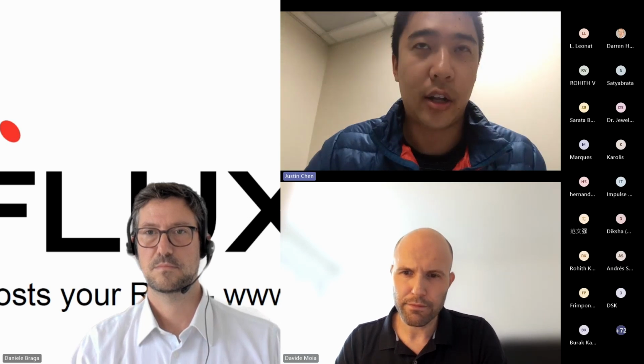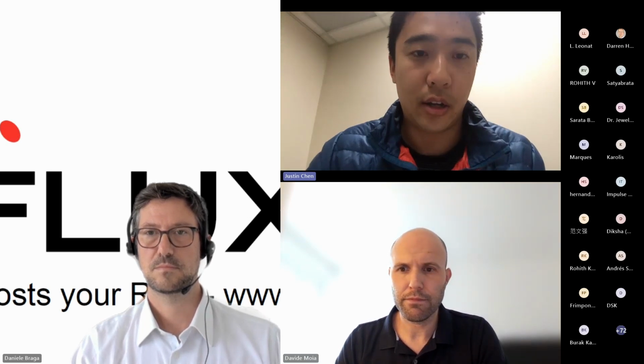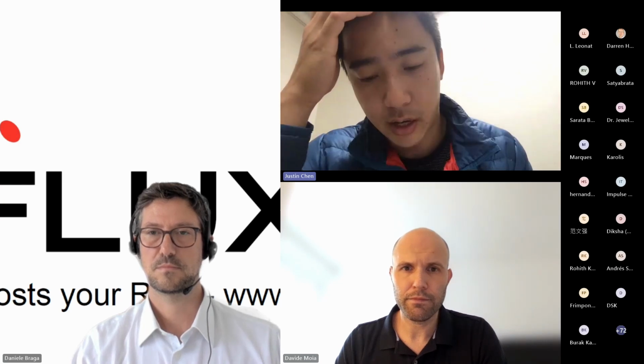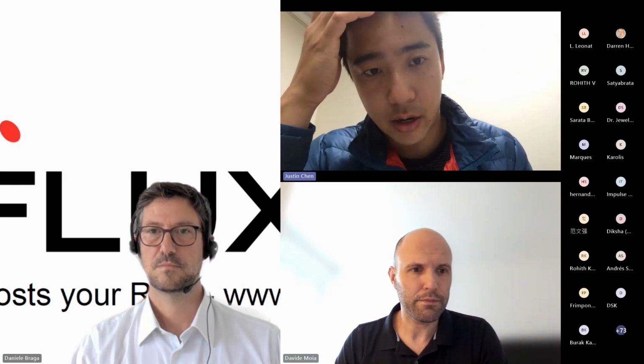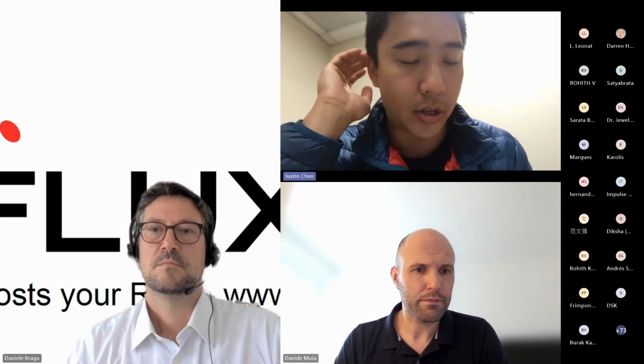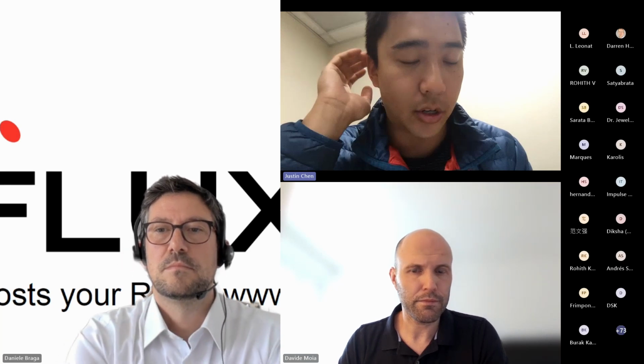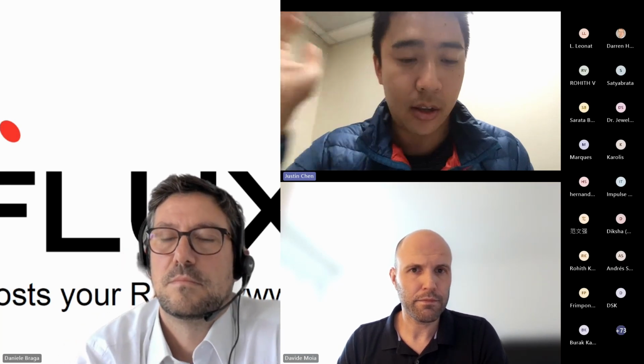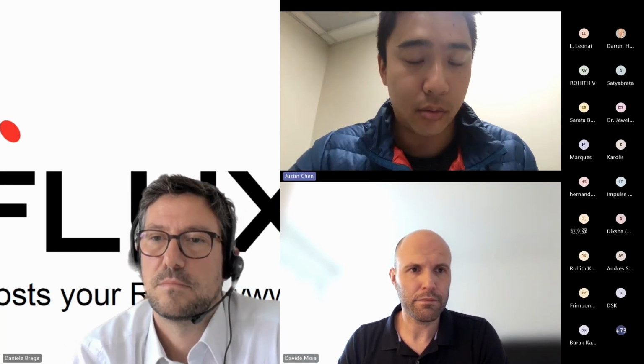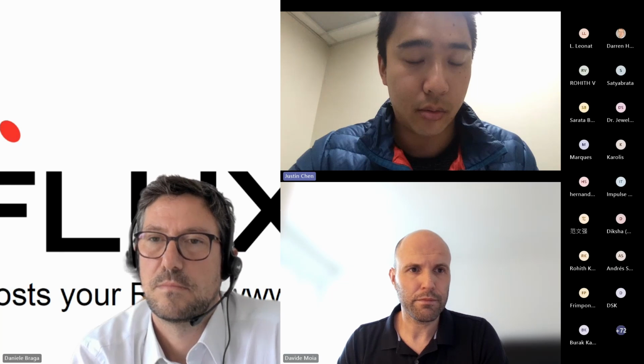And the concentration is about 1.5 molar. So it's quite thick. I think a lot of people who are achieving the higher efficiencies now are using a much higher concentration, because you can get something about 800 nanometers of perovskite, and that will really help boost your current. But of course, the fill factor can be difficult to keep high at the same time.